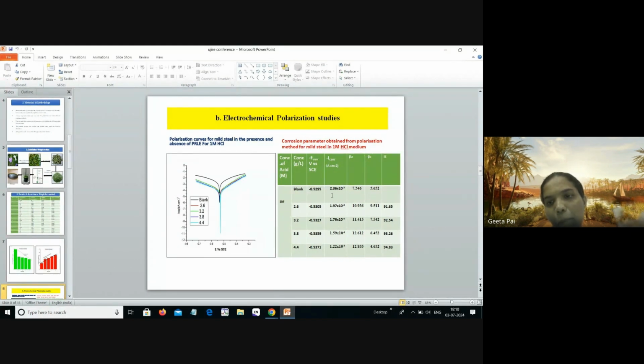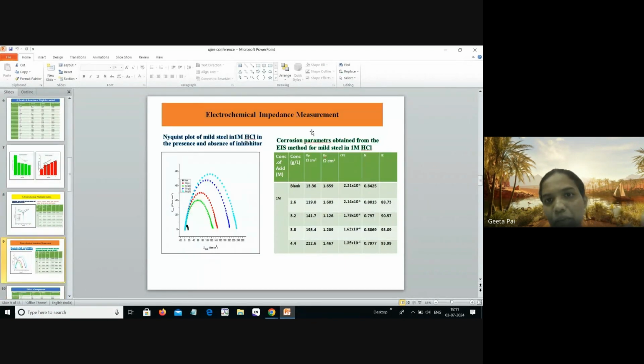It means that the metal dissolution process also decreases. The hydrogen gas evolution process also decreases. Hence, it can be concluded that the inhibitor will inhibit both the cathodic process as well as the anodic process, and it will act as a mixed type inhibitor. Then it can be further confirmed by the potentiodynamic polarization technique.